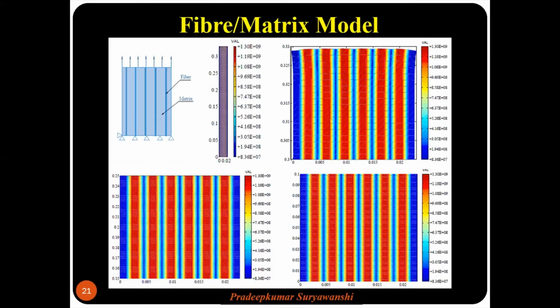Further, we considered the composite material, and in case of our model, we modeled it as a fiber matrix model. Now, what I mean by fiber matrix model is that let's consider lamina of composite material, and with these boundary conditions and loads, here we consider unidirectional fibers as shown in this figure, and for simulation purpose, again we consider glass epoxy with fiber volume of 33%. That means 33% of the total material will be fibers. And in order to simulate that, we considered every third fiber in the mesh, every third column in the mesh as a fiber.